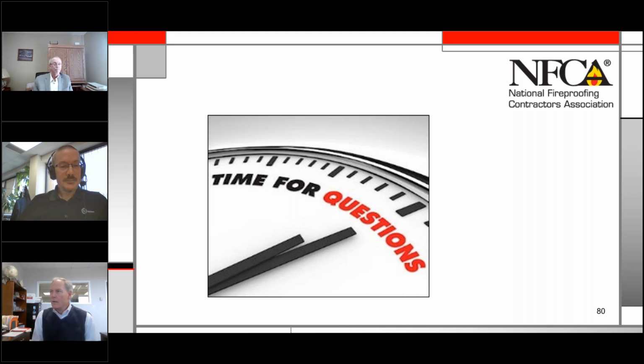Okay, got it. Similar to question 1, when the thickness is calculated in inches, is everything rounded to the 1/8 inch lower side or up to the higher side? I'd say look at the BXUV guide. I think in most cases it's rounded up to the nearest 16th, just to be conservative. But check the BXUV guide. There might be other situations where you don't have to. That's usually for SFRMs. That's how those are broken down into the nearest 16th of an inch. Okay.